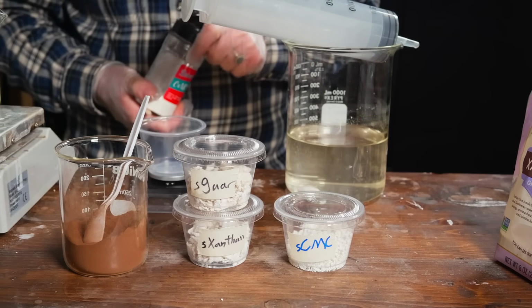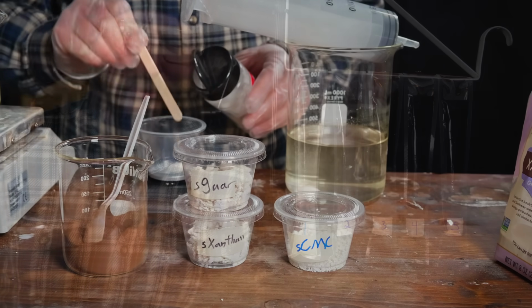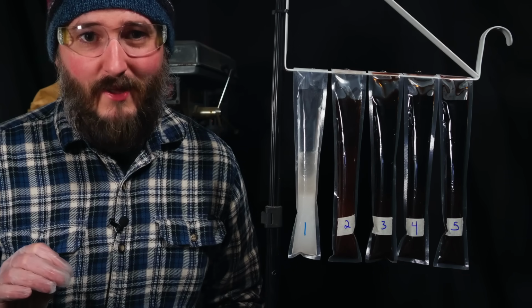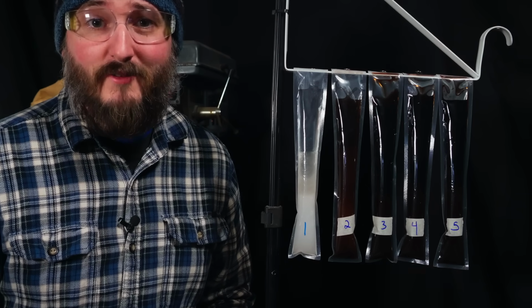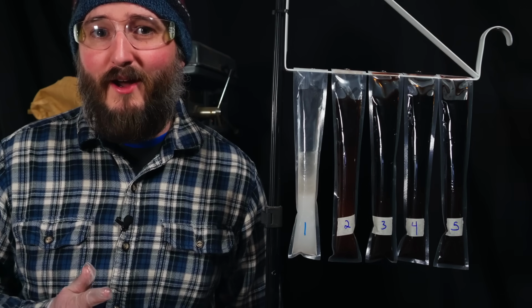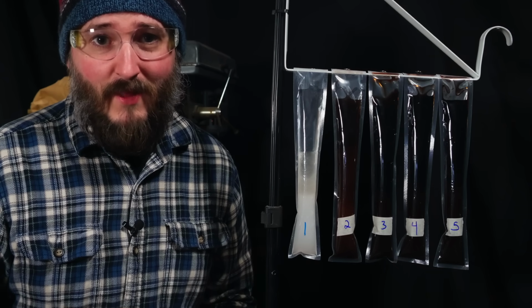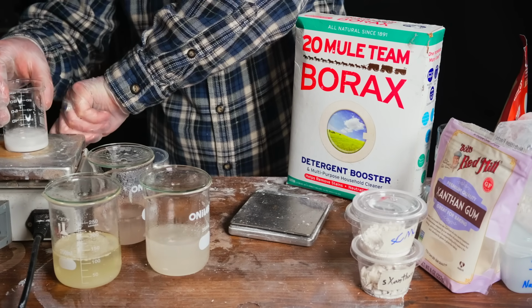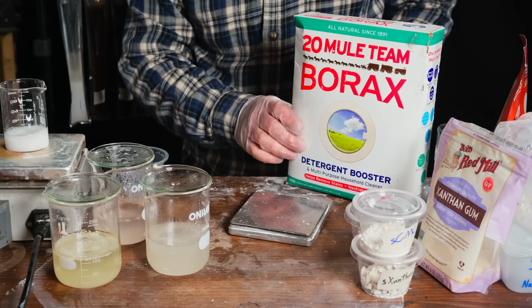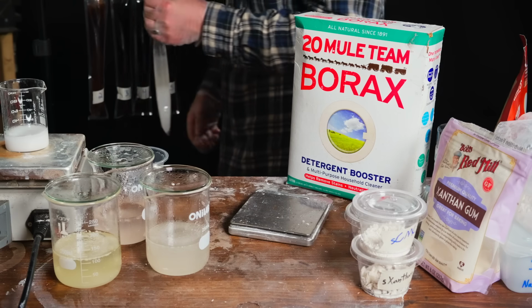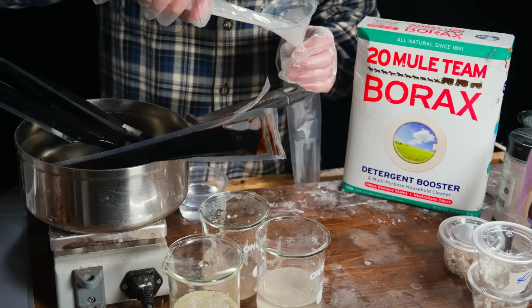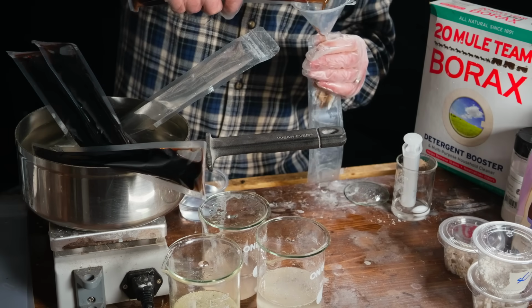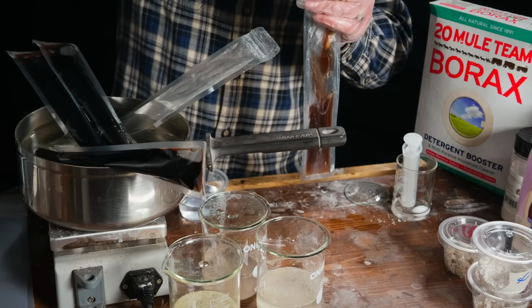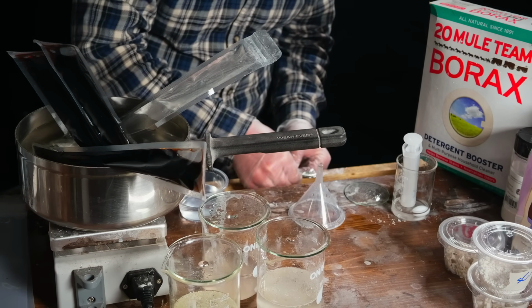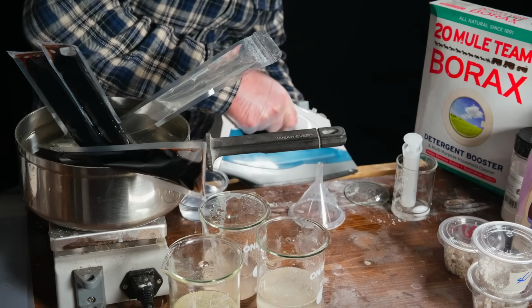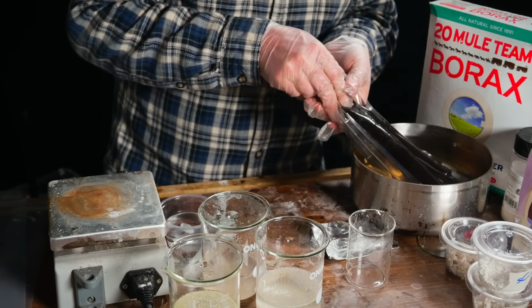To fix this problem, some gelling agents like CMC do help the solution to freeze at the right temperature, but you can also make this happen with dedicated nucleating agents that trigger the hydrated salt ice to start forming at the right temperature. It only takes one little speck to convert from liquid to ice phase to trigger the entire solution to rapidly freeze. So I added a nucleating agent to each sample after remelting them, that being 1 gram of borax. This is known to be a very effective additive to prevent supercooling in PCMs, but I've really tried to avoid using it because recently it's been banned in most of Europe, and I prefer to use things that are accessible to everyone. There are other alternatives, but in this case, borax was the quickest way I could think of to solve the supercooling issue so that our sulfonated additives can be tested under normal freeze-thaw conditions. So we'll let these samples cool back down, and then the results should be more telling.